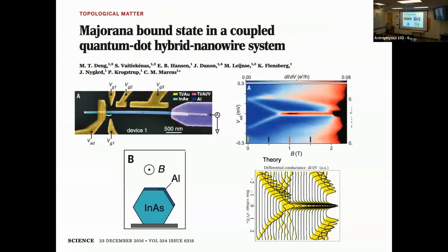Our first round of experiments was 2016. This was following the 2012 work from Delft, which did not have access to these semiconductor materials, they hadn't been invented yet. And we use a wire that has the superconductor on two facets of this hexagonal cross-section nanowire, and found that as we turned up the magnetic field, at just about the magnetic field where you would expect the Zeeman energy to equal the superconducting gap. These two subgap states came down, met in the middle.